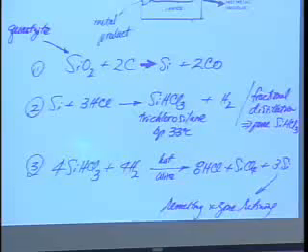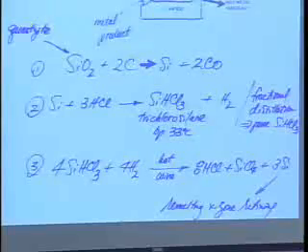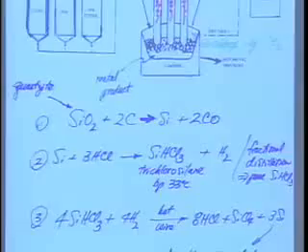And the molecules of trichlorosilane hit the hot wire in the presence of hydrogen, back react to form HCl, silicon tetrachloride, and silicon. And it's this silicon that comes out of that first operation that then goes for subsequent zone melting to make the giant single crystal from which we cut this piece right here. And all of this goes back to the 1800s.